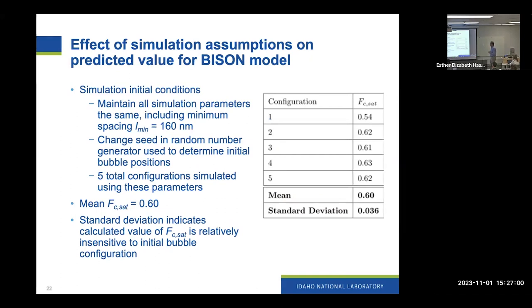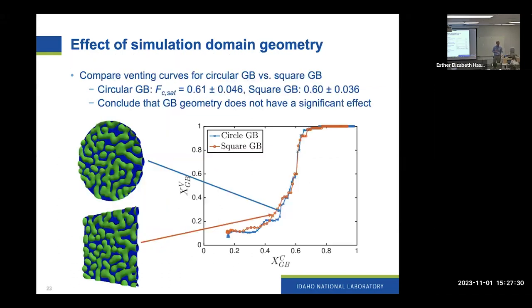So we ran several different initial conditions, and tried to figure out an average. I know this is not a tremendous amount of data from which to derive a standard deviation, but it does give us at least some sense of the uncertainty in this value that we're calculating. And it's relatively insensitive to the initial bubble configuration. So that's good. I think that gives us some confidence in the value that we're using.